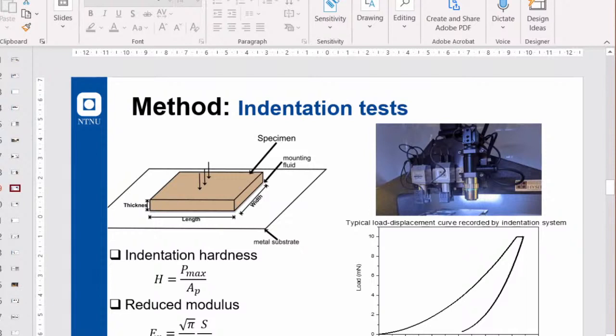And then typically we're staying within the 5%, 10% rules. So for this case, we got a little bit deeper. If the indents got deeper than what should happen, we didn't actually use that data set because we were trying to look at these as if they were also a coating so that we didn't get any substrate effect. Okay. I see that the maximum depth here is around 1 micron, isn't it? Exactly. Yes. Yeah, it's good. Thank you. Very nice. Thank you.